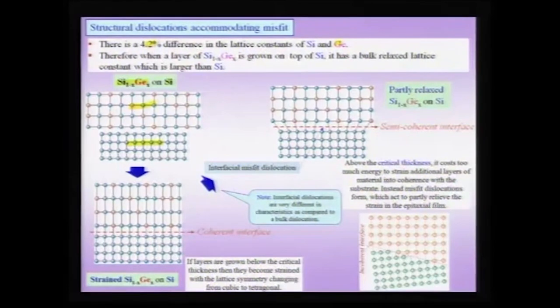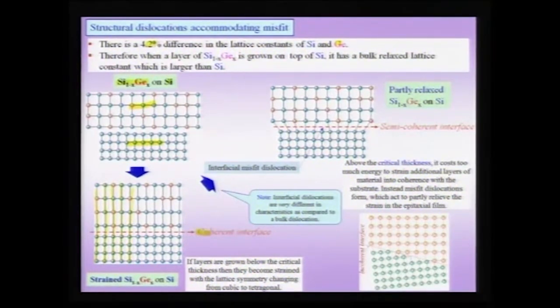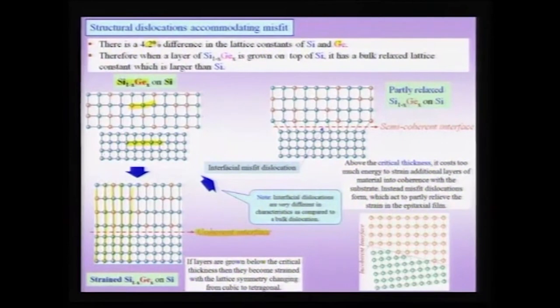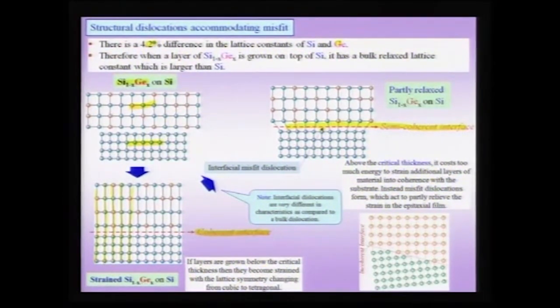You can see in the schematic that lattice planes are continuous, and such a boundary is called a coherent interface or a coherent boundary wherein lattice planes are continuous. The GeSi alloy grows epitaxially on silicon, putting out a coherent interface. But as the film grows thicker and thicker, at some point the energy stored in the film becomes too large. Therefore the interface breaks up and becomes what is known as a semi-coherent interface. In other words, a coherent interface becomes semi-coherent by the presence of a misfit dislocation, and this edge dislocation accommodates the linear misfit between the epitaxial film and the substrate.